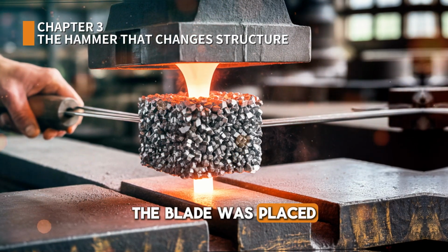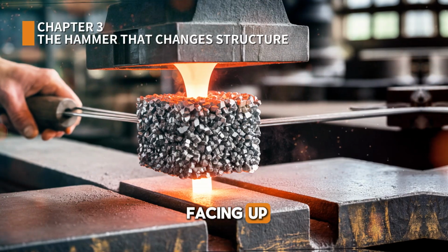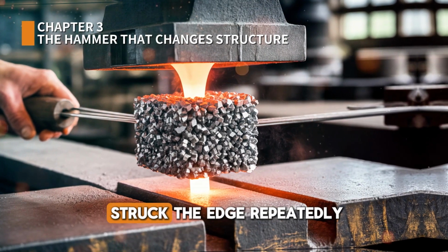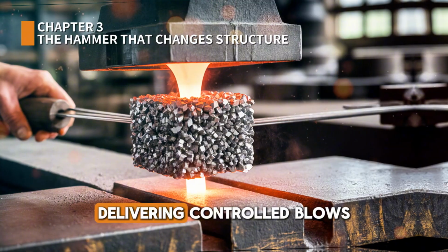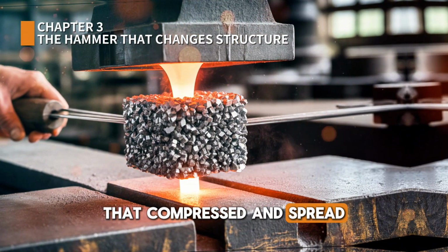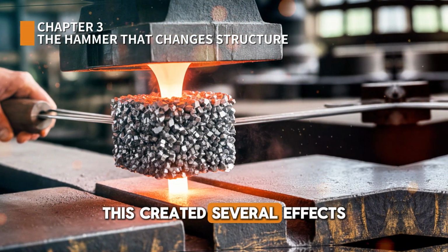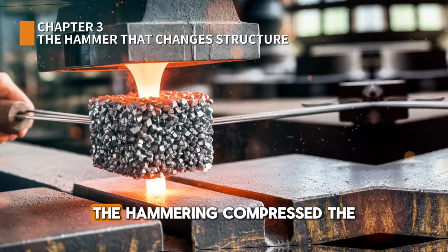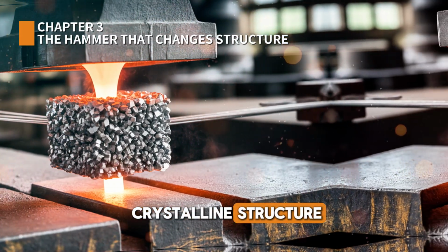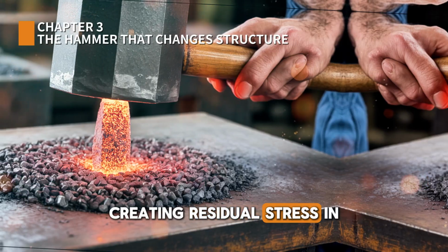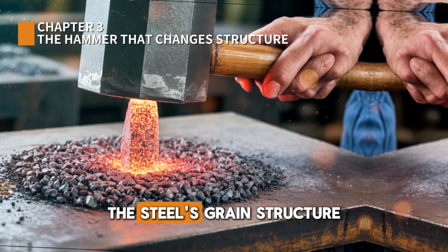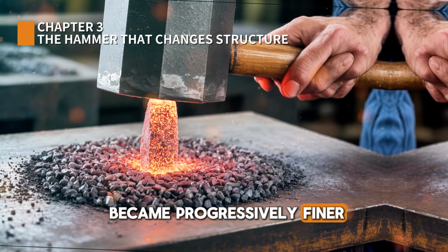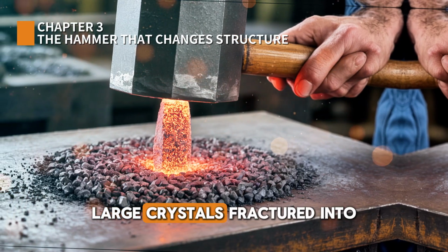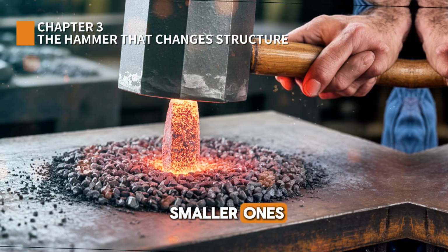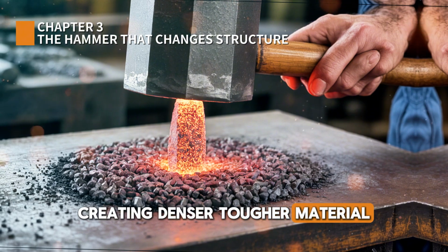The blade was placed on an anvil, edge facing up. A narrow-faced hammer struck the edge repeatedly, delivering controlled blows that compressed and spread the steel. This created several effects. First, the hammering compressed the crystalline structure, creating residual stress in the edge. The steel's grain structure became progressively finer, with each blow large crystals fractured into smaller ones, creating denser, tougher material.